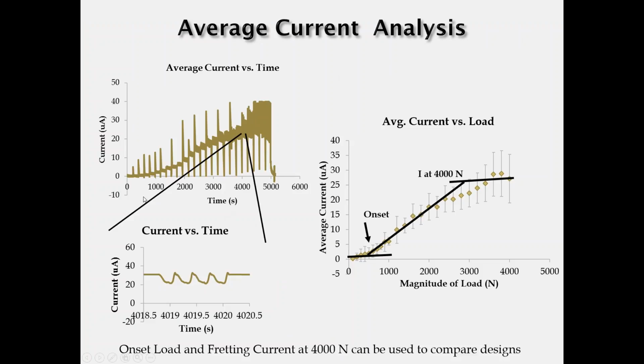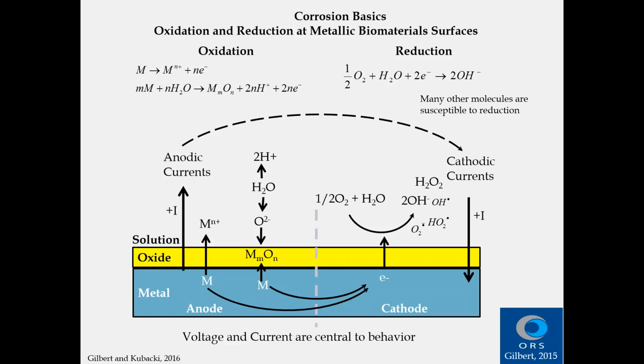And so you can see there are spike transients when we change the magnitude of the cyclic load, average or mean current levels that rise as we increase that load, and there is a load at which the fretting currents begin to occur. And so we can look at that onset load, we can measure the current at the maximum cyclic load that we apply, and so these are measures of sort of the performance of that modular taper that can be used to assess materials, assembly, other surgical issues, and the factors that might impact on modular tapers.